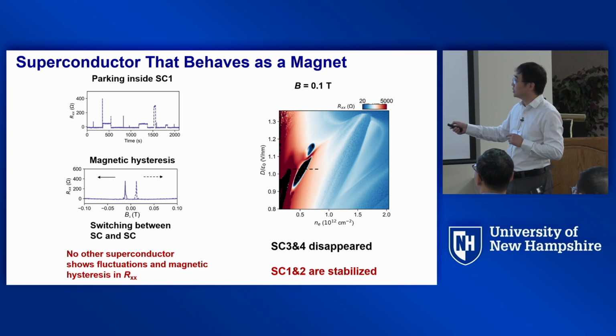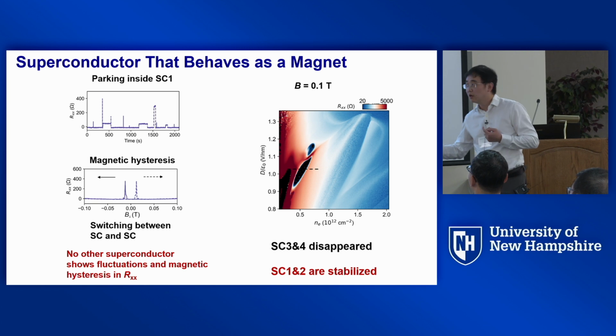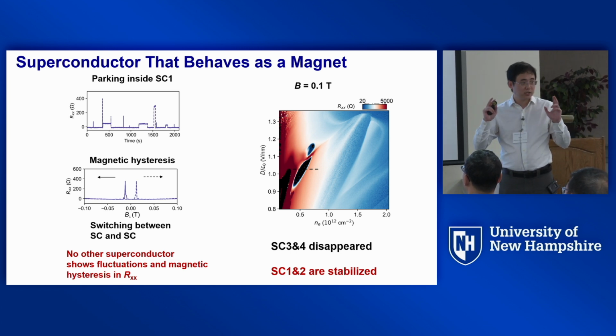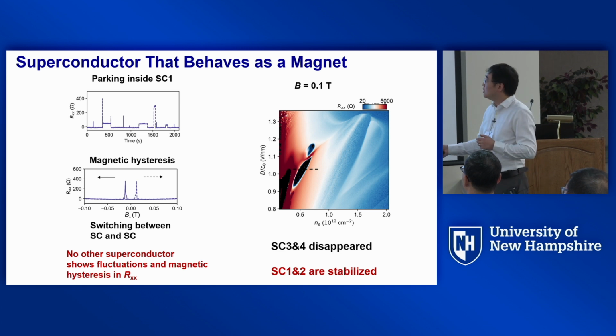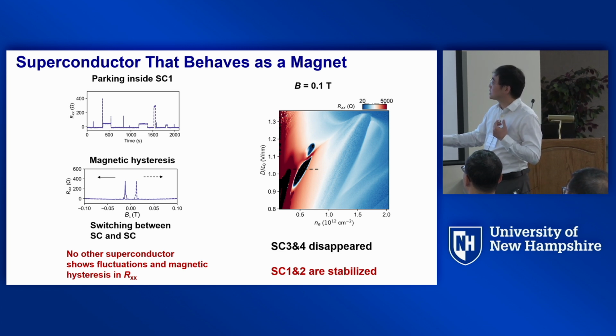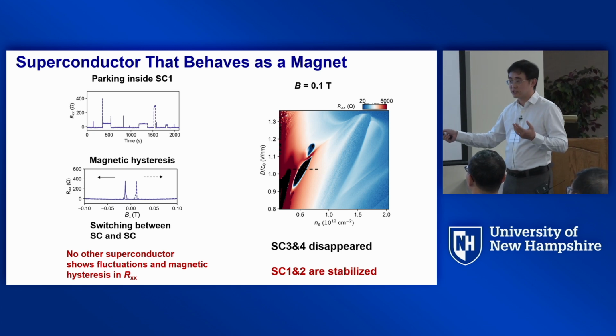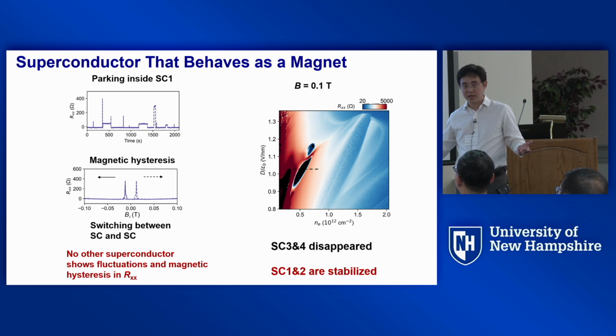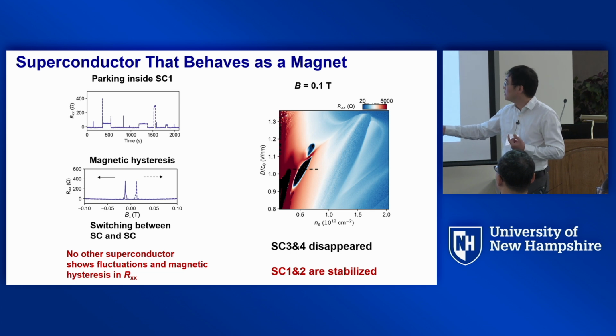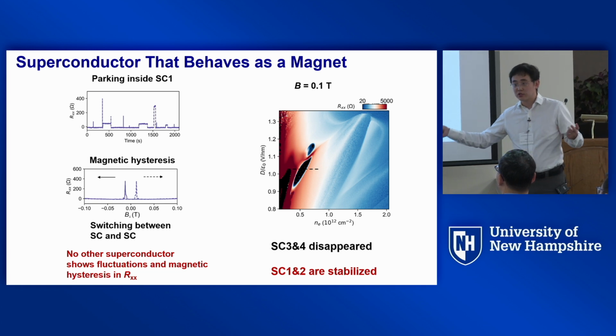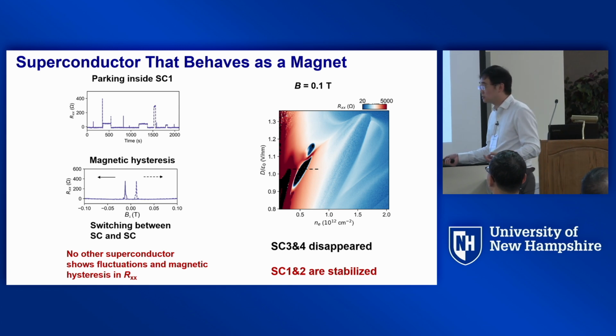Most of the time, the resistance is 0 in the superconducting state. From time to time, it jumps, deviates from 0 briefly and comes back, and this peak height varies from case to case. So it is a temporal fluctuation, not a fluctuation triggered by scanning something. Secondly, you park in the same state, and now you scan the out-of-plane magnetic field back and forth, negative, positive, positive, negative, and you observe hysteresis. What do I mean by hysteresis in a 0 resistance state? When you switch something by the magnetic field, the whole thing becomes temporarily not superconducting, and you have a finite resistance peak there. And that tells you, scanning forward and backward, there's a hysteresis.